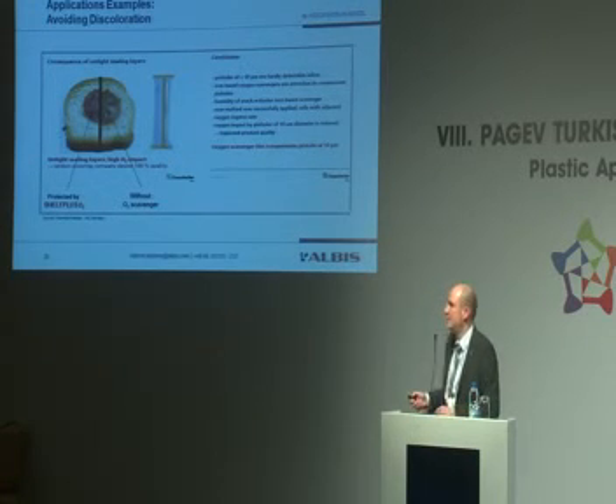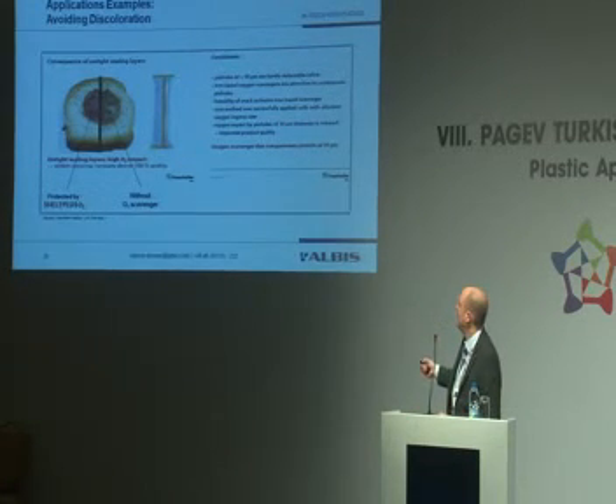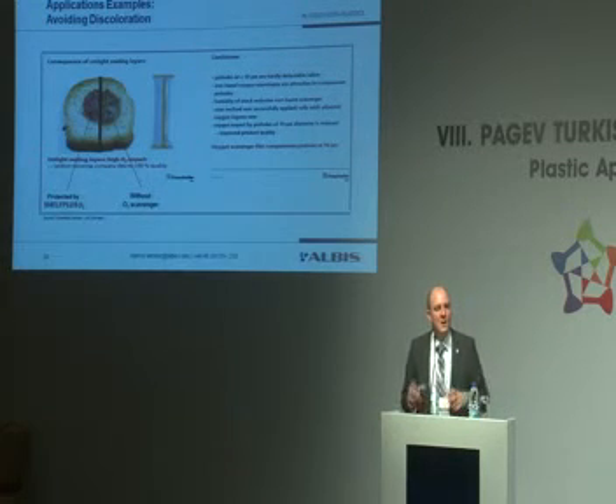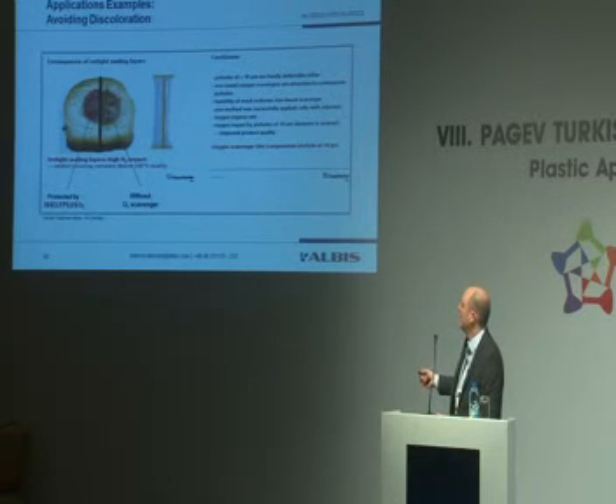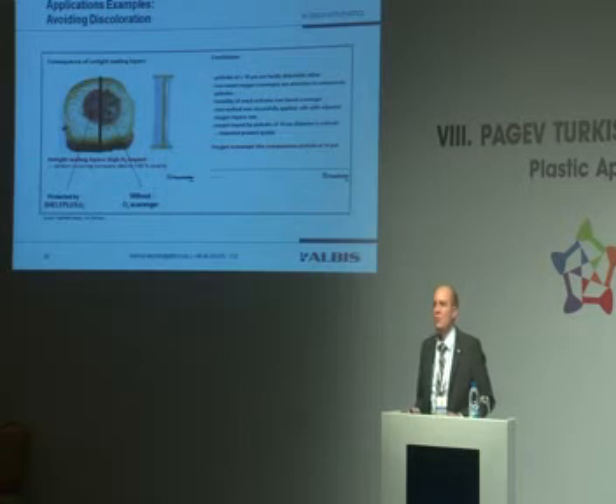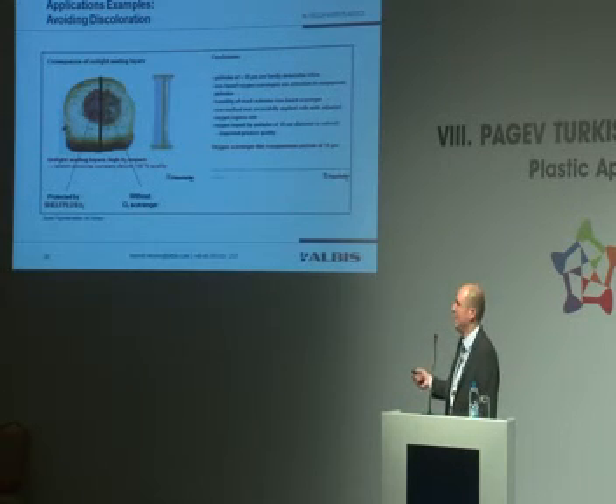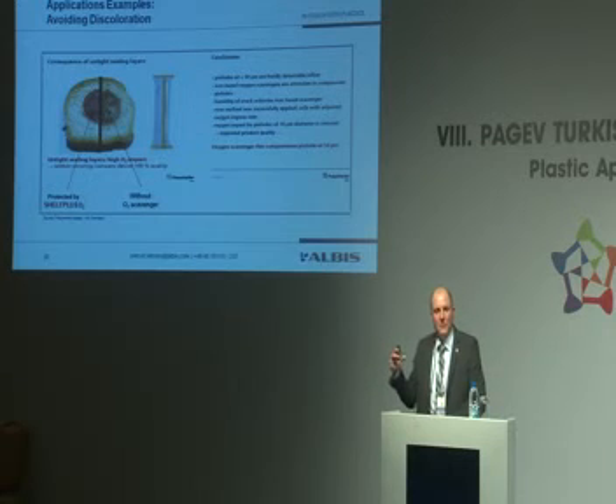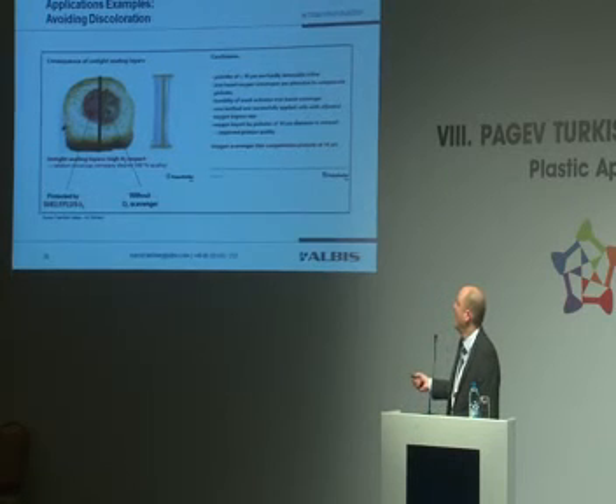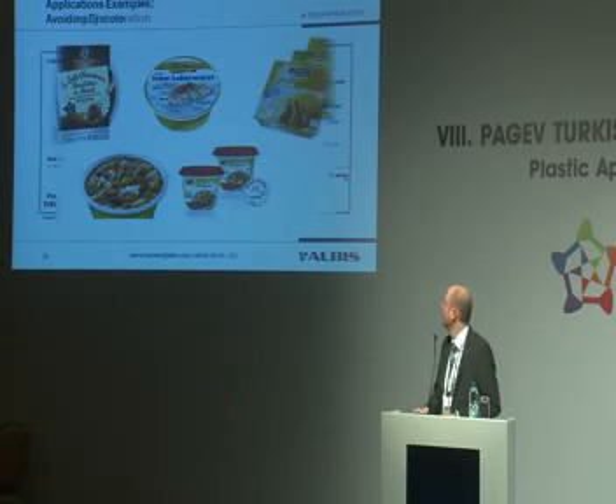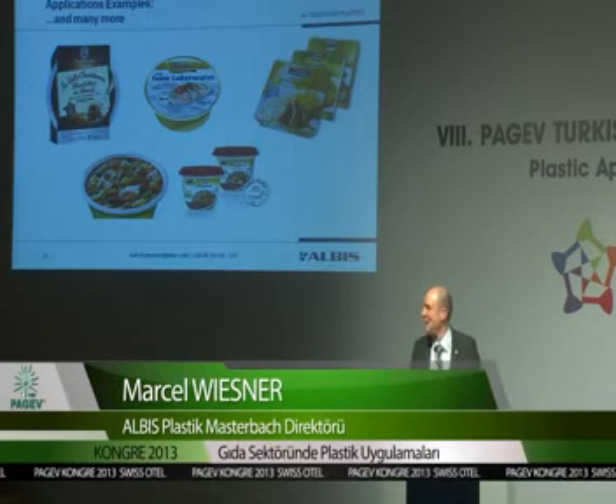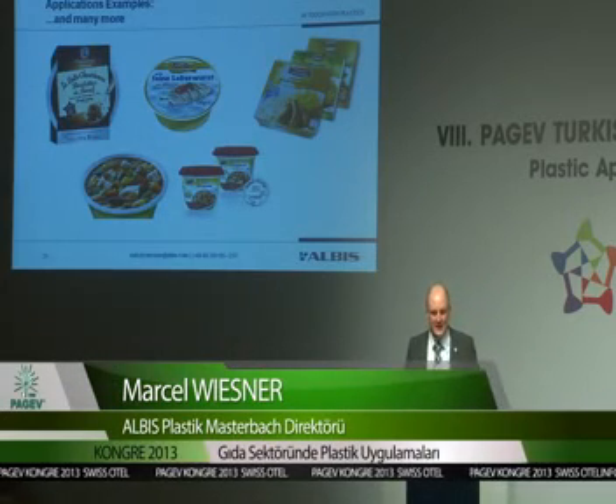Another thing, if you have these welded pouches, you can have pinholes in the weld line. Those pinholes carry oxygen that can arrive inside the packaging volume of the pouch. And in this application, a sausage roll, this led to a significant discoloration. Now, if you add an oxygen scavenger to the packaging film, it's also here in the welding line, the pinholes are still there, but if the oxygen is inside the pinhole, it's absorbed, so it doesn't reach the inside anymore, and you don't have the discoloration. So, and that's it. And a little bit more possibilities that can be done.